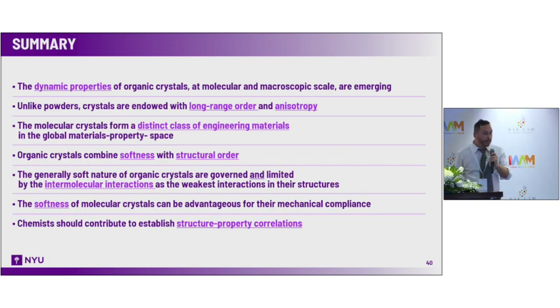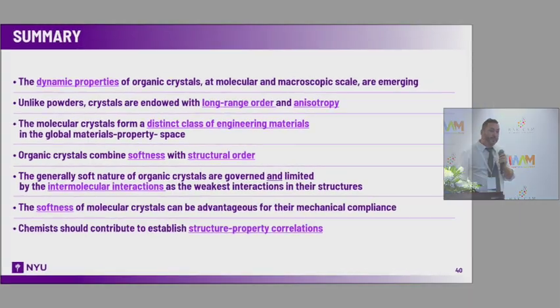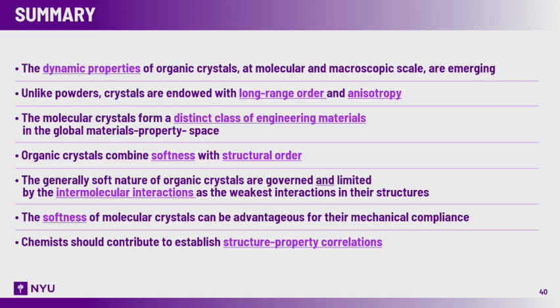So I would like here to summarize my talk and tell you that dynamic properties are important, not only for molecules and for other soft materials like colloids, but also for crystals. The biggest asset of crystals is their long-range order, and this gives us a chance to transfer energy much more rapidly and efficiently. The anisotropy in their structure is really important because this means we can control the properties, or we can elicit properties in different directions. So we would like to be able to set crystals as a separate class of engineering materials, to set performance indices and bring these to the attention of the engineers who will be using them for other applications.